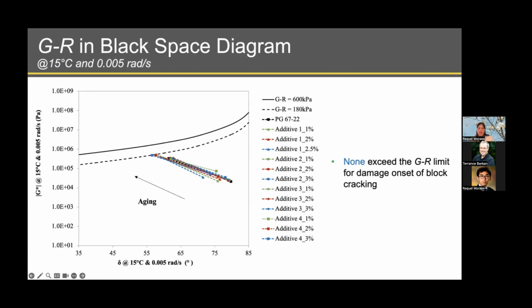limit where if a binder, neat binder, exceeds that bold line, it should already be showing visible cracking in the field. And if it's between these two lines, it means that the cracking is initiating, beginning to propagate. And if the binders are located below the dashed line, it means that we are good, no potential for cracking.